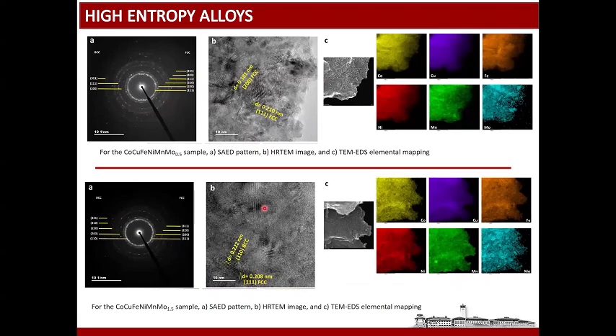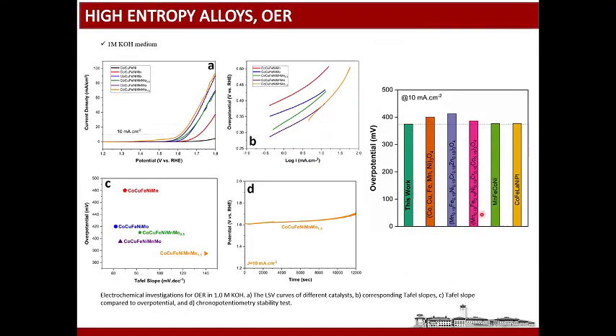So we did TEM analysis and we observed these different FCC and BCC structures as well. We also did EDX analysis, and as you see in the EDX analysis, all the metals are homogeneously distributed in the particles. So there is no segregation of any structure in the alloy, but homogeneous distribution of all metals in the alloy.